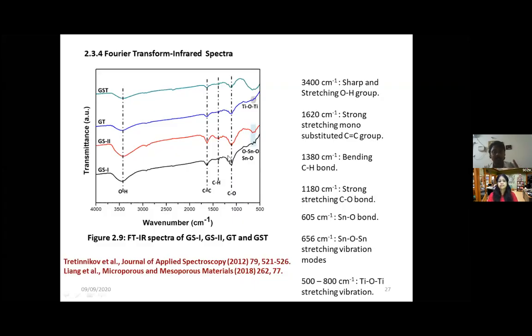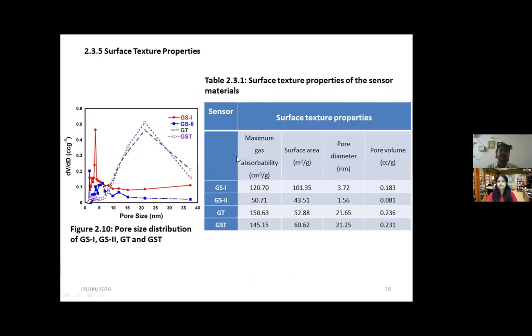The second one: what are the surface functional groups that are present on the sensor material surfaces. And the last characterization technique is the N2 adsorption desorption isotherm. This tells about the surface structure properties, that is, what is the maximum gas adsorbability. We use nitrogen gas here to ensure the surface structure properties. What is the maximum gas adsorbability? It's surface area, pore diameter, and pore volume here.